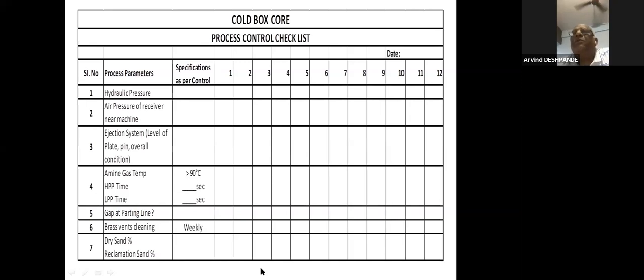Normally what happens, the amine gas heater is far away from the machine. Actually, it should not be. It should be as near as possible, because after the heater, if the length of the pipe is more, there are chances of the temperature dropping. That care has to be taken. Then HPP time, LPP time as per the type of core, type of machine, and machine parameters has to be checked. Then no gap at the parting line. Then brass vent cleaning. This is most important because, as compared to shell core, the flowability of core box sand is comparatively much less. So to get a dense core, brass vent cleaning is the most important activity.